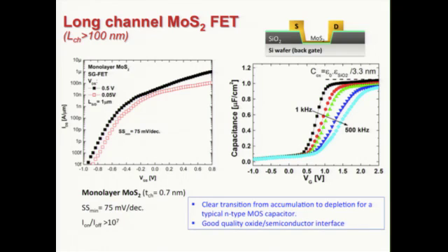Well, the device structure is like this. We use highly doped silicon as a back gate, and then we have a thin layer of hafnium oxide as the gate dielectric. We transfer the channel, and we have this thick silicon oxide as an isolation layer, so that it basically separates the measurement pad from the gate.